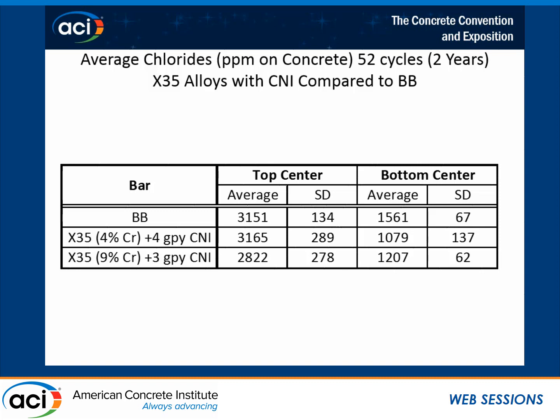And look at these standard deviations, in the order of 10% or less. They're very tight, the amount of chloride on the cracked samples. It's not like one sample has a very high chloride content and the other very low. They all come out fairly tight relative to each other, 10% or less of the amount of chloride there. When you get over to the bottom center, you can see there's still about half the chloride here that there was at the surface. This is 5 inches down, so it's roughly 4.75 inches below the crack, almost.